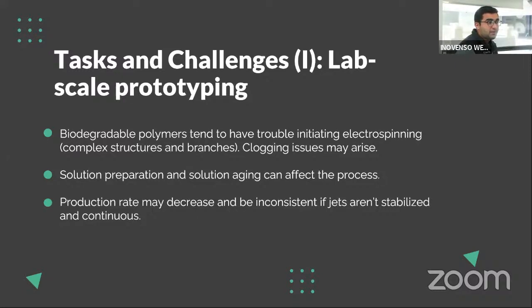The first challenge I would have to say is that biodegradable polymers tend to have an issue initiating their Taylor cone. At least 3 out of the 4 aforementioned polymers, we had issues with that. That could be attributed to their complex nature, the structures. They tend to have a strange emission jet formation, and you can't really control their jet that well, and because of that, clogging issues may arise. That's one challenge you're going to face if you're looking at electrospinning biodegradable media.